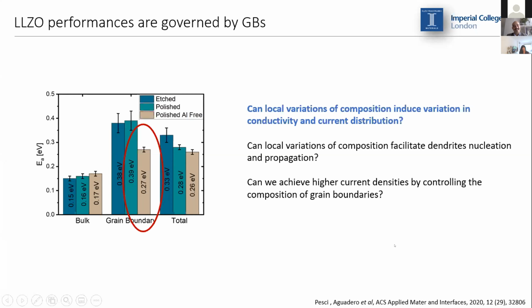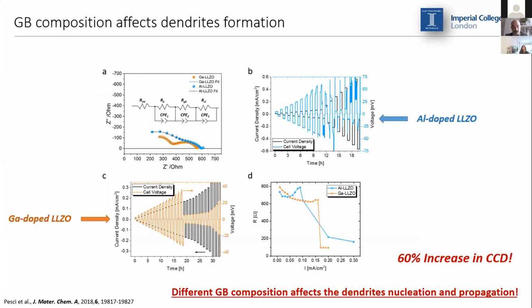So again, they led to some questions. So it's actually the amount of aluminum that we've got in the grain boundaries that can have an effect on the activation energy. And if that is what is happening, can they have an effect on the electrochemical performances of garnet? I mean, if we change the composition of the grain boundaries, can we actually play with the critical current density for dendrite formation? And to investigate that, we actually took a few samples.